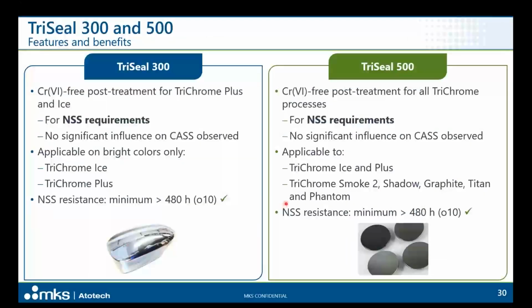But of course, when we are talking about chrome-free or chrome 6-free plating processes, we need to consider also the post-treatment after the trivalent chromium process. These post-treatments are recommended when we need to fulfill the requirements in the field of neutral salt spray corrosion resistance. And here, MKS Atotech can propose two options. One process is the Tri-Seal 300.